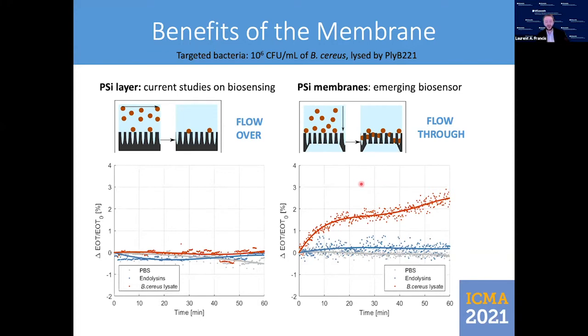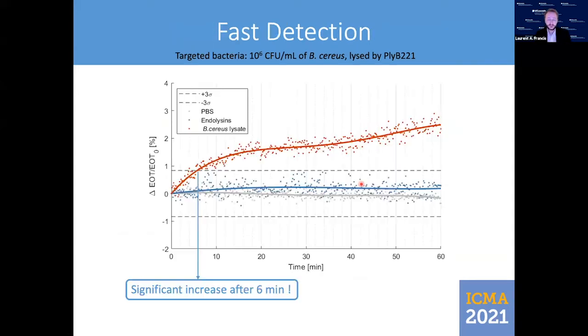Knowing that 1 hour of detection corresponds to the filtering of 1 milliliter of our bacterial lysate. Now let's take a closer look at the graph. In gray, we have the negative control with only the buffer solution. This induces a slow decrease of the relative effective optical thickness, which can be explained by the slow dissolution of the silicon oxide in the saline aqueous medium.